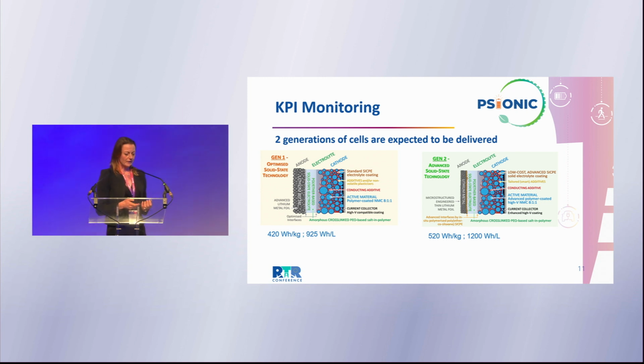So here you can see the details on how we are intending to do that. To move from 900 to 1,200, we need to work a lot on the lithium metal first. So we will reduce the thickness, but if we only reduce the thickness, you all know that it will never cycle for a long time. So we engineer this lithium metal, we improve the interfaces, we coat it to make it work better.